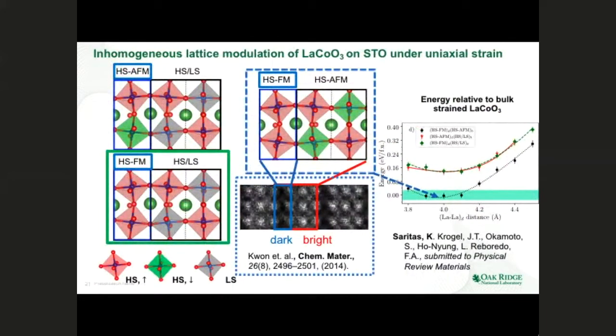So going back to our main motivation, we wanted to understand how this lattice modulation works in these materials. We basically wanted to simulate how this structure is formed from the theoretical perspective. So we studied 3 different scenarios where we separated our simulation cell into 2 regions, where the left side is the dark region and the right side is the bright region. And we optimized these geometries at the DFT level because these cells would have 30 atoms in them. This would be too complicated for diffusion Monte Carlo calculations.